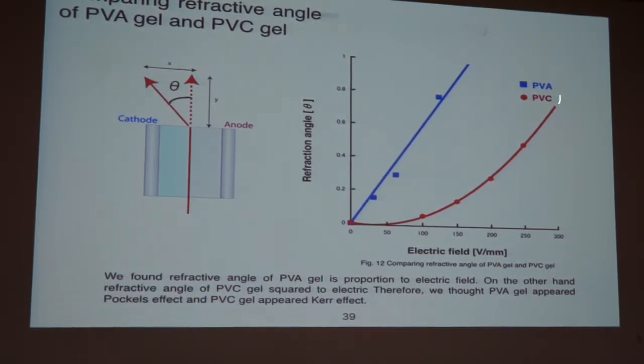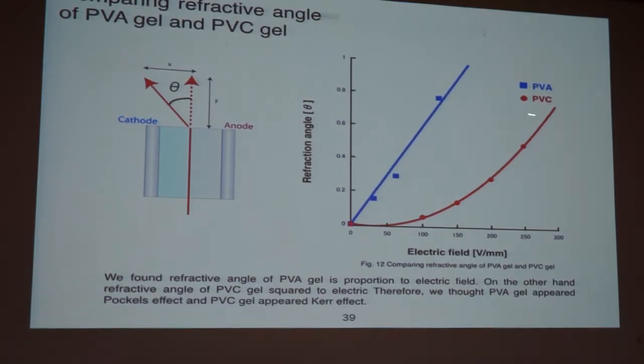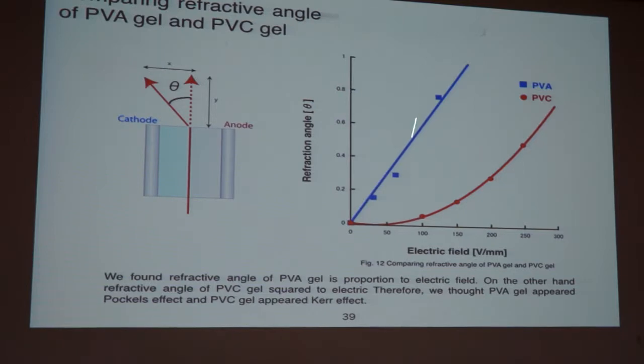So the polymer gel is generally the same, but the structure of the gel is totally different between these two. And from the viewpoint of optical function, this material will be better because the refraction is not that big, but PVA shows very efficient deformation. But for durability, this is much better. So it depends on the use, what kind of field we are seeking is important.